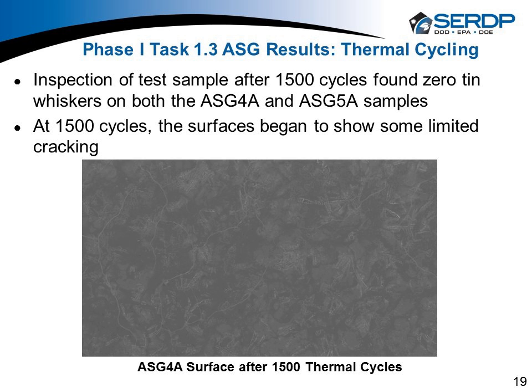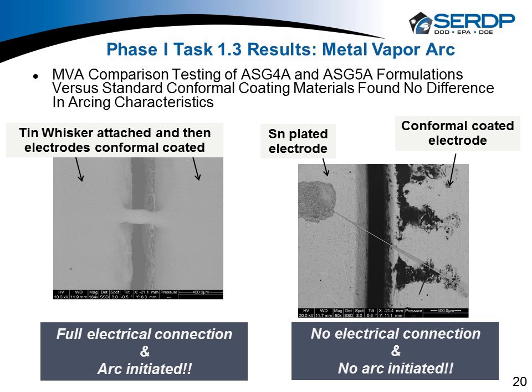So even after 1,500 hours of this, which is roughly about 3 months of continuous cycling, you can see here on the photograph, there are some cracks that showed up, but they're very slight. In fact, there's less cracking than what we saw after 500 hours with the ASG4 coating, and way less than we saw with the ASG5 coating. So we wanted to prove that we couldn't spall this coating off, that it was well adhered to the leads, the metallic leads on the components on the plastic. And we didn't do any more thermal cycling after we finished this. We put all our efforts into the high temp, high humidity testing.